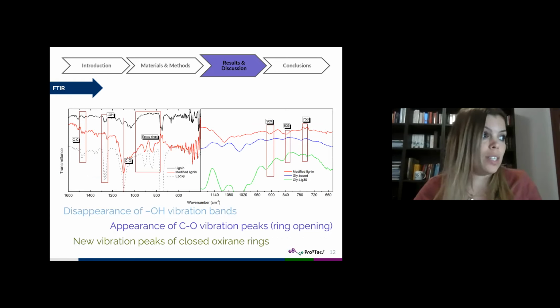As can be seen in the figure, the chemical modification of lignin can be verified by means of the disappearance of hydroxyl bands. In the black line, we can see the vibration of the hydroxyl group, which has disappeared in the red line. Also detected is the appearance of new peaks related to the CO bonds resulting from the epoxy ring opening. This allows us to verify, therefore, the chemical reaction occurring between open epoxy rings and hydroxyl groups of lignocellulosic materials.